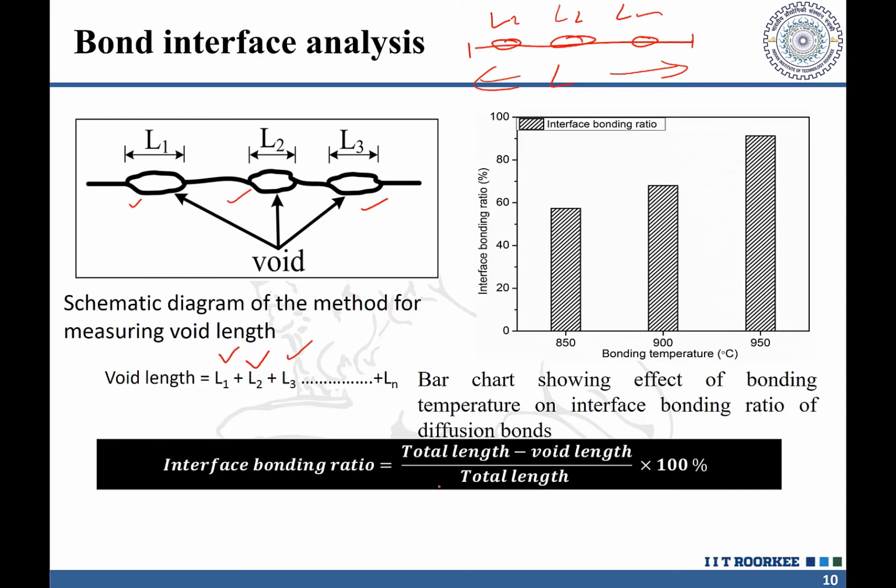So the total length being investigated has to be used, along with the total void length, to see the interface bonding ratio, which is the percentage length of the interface that has been bonded. The total length minus the void length, divided by the total length, gives us the interface bonding ratio. Say the interface bonding ratio is 60 percent at low temperature, and this will be increasing